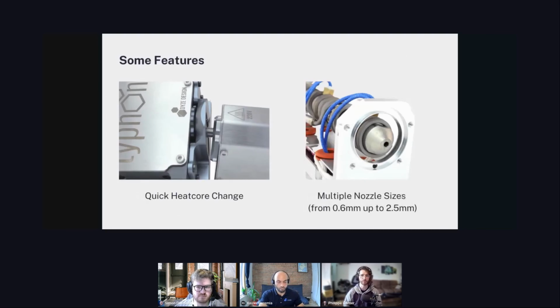Each heat core can be switched easily with a knob turn, removing the whole heat core rather than the nozzle, to prevent any leaks or problems from the end user manipulation. The abrasive-resistant nozzle prevents any changes in nozzle size and height during a large print with abrasive filaments. Sizes are available from 0.6 millimeter to 2.5.